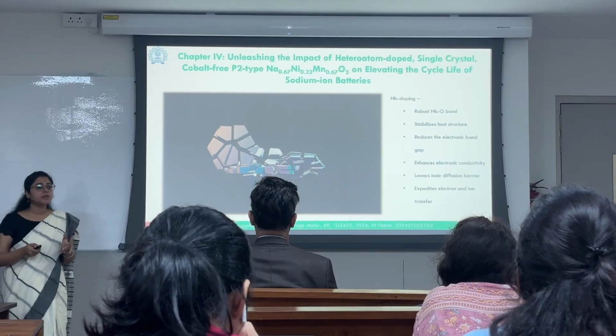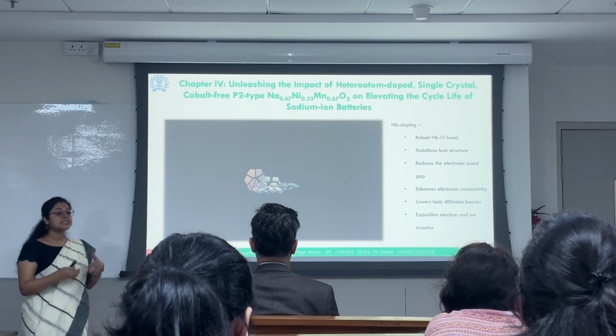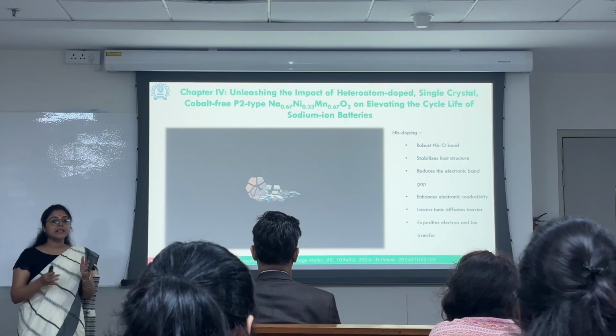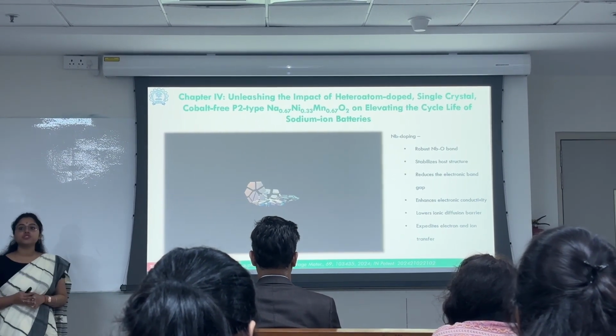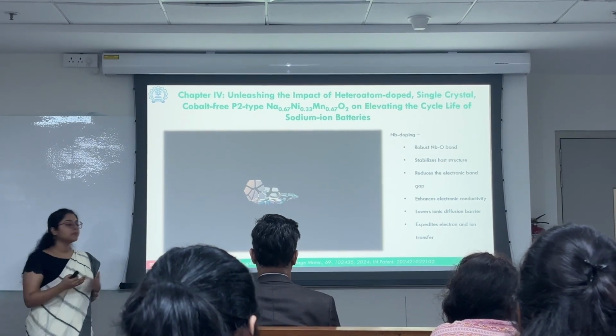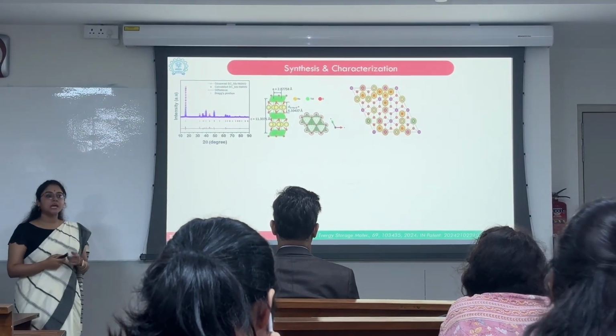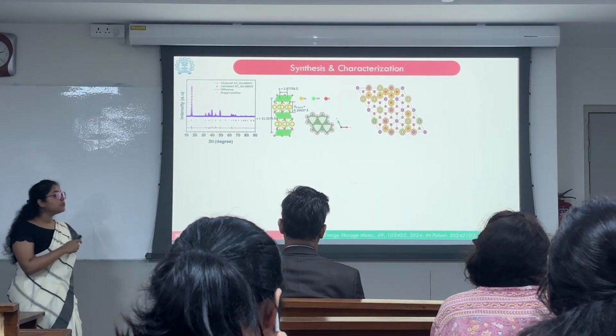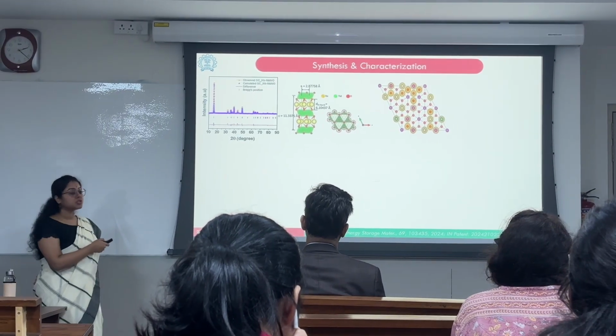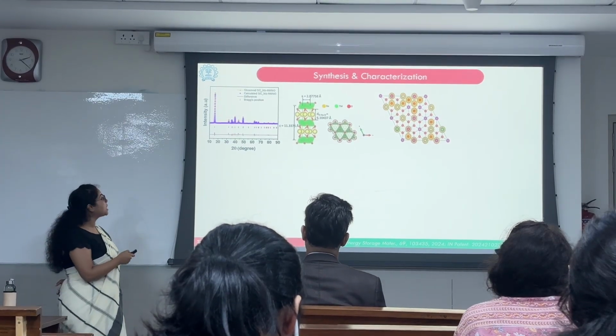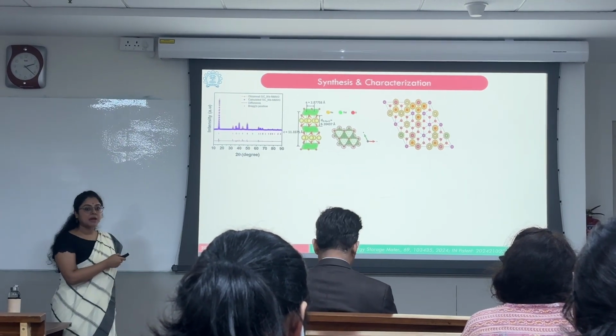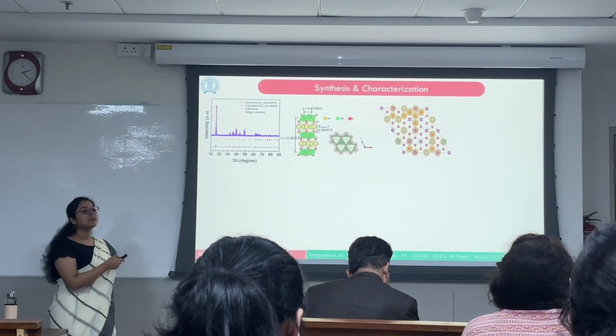We have chosen niobium because of its robust bond with oxygen that stabilizes the host structure, reduces the electronic band gap that would improve the electronic conductivity, and also has a lower diffusion barrier, thereby expediting the electron and the sodium ion transfer. So we start by synthesizing the niobium-doped NNMO cathode, and the phase confirmation was done through XRD refinement. And when we visualize this XRD refinement through the structure, we observe that doping niobium has increased the c-axis parameter, reduced the a-axis parameter, and also increased the sodium-oxygen bond length.